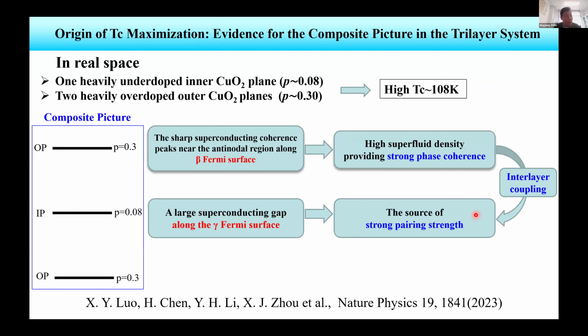I think our results on Bi2223 are very consistent with this composite picture. In real space, we have three CuO2 planes. The inner plane has a doping of only 8%. The other two planes each have a doping of about 30%. One is heavily overdoped, the other heavily underdoped. Each of them alone doesn't superconduct at all. Like 30%, they don't superconduct. 8%, heavily underdoped, is near the border of becoming superconducting, but TC must be very low. But if you put them together, there's some interaction between them. Actually, TC is very high. It's 108 Kelvin. So I think this is consistent with the composite picture proposed by Kivelson.